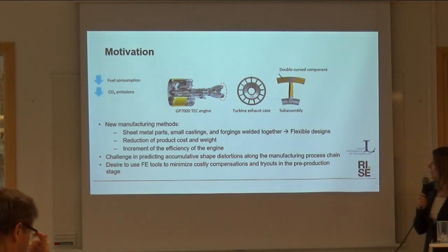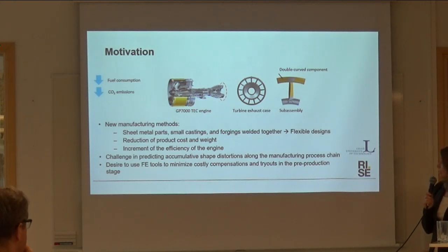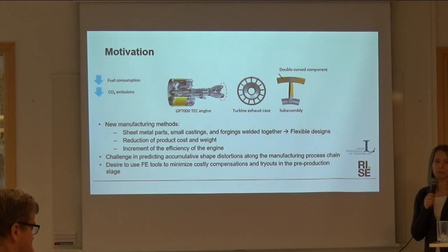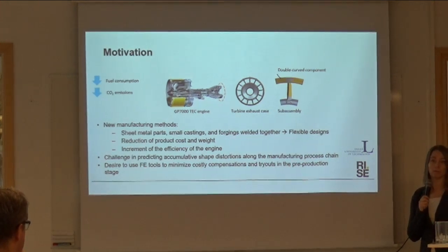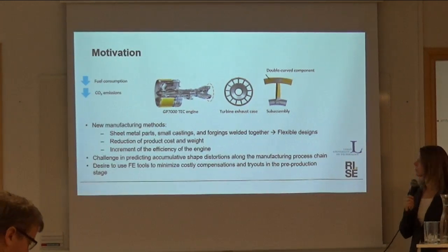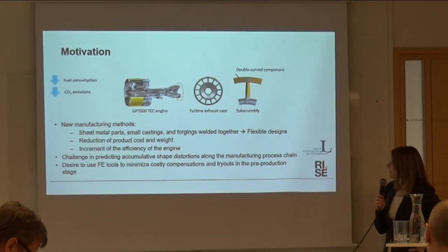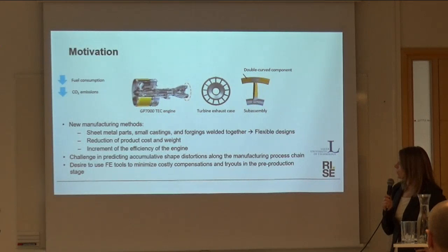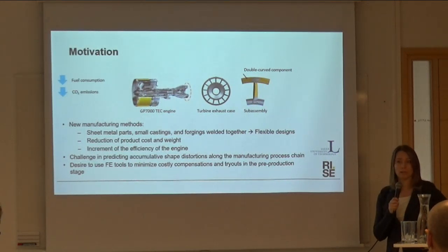And the challenge in this project was to predict the accumulative shape distortions which take place in the forming, welding and heat treatment procedures, and to be able to compensate for those using finite element model computer simulations. And by that, contribute to minimizing costly compensations and tryouts that they face in the pre-production phase or in the development phase.